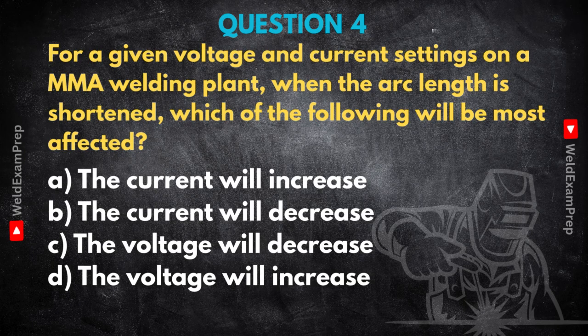If I is constant and R goes down, V must go down too. Bingo. To maintain that constant current flow across a lower resistance, the power source automatically decreases the voltage across the arc. So the answer is C. The voltage will decrease. That's the one. The current stays relatively constant because it's a CC machine, and the voltage drops because the arc resistance dropped.